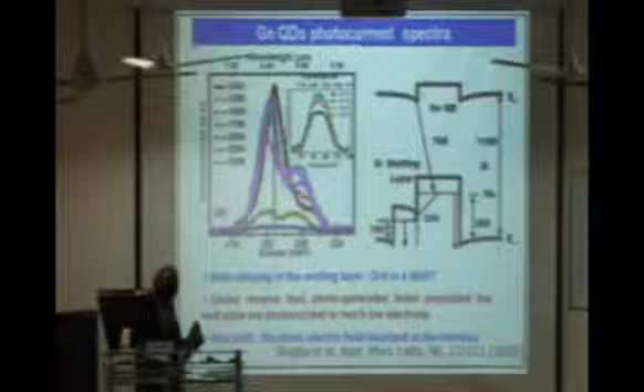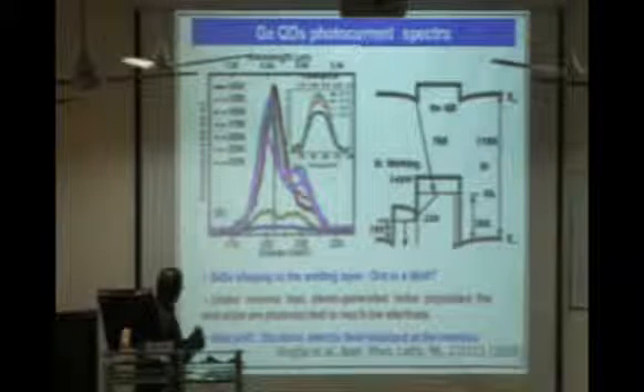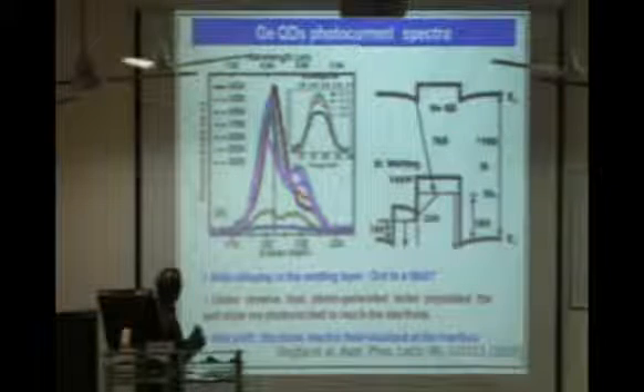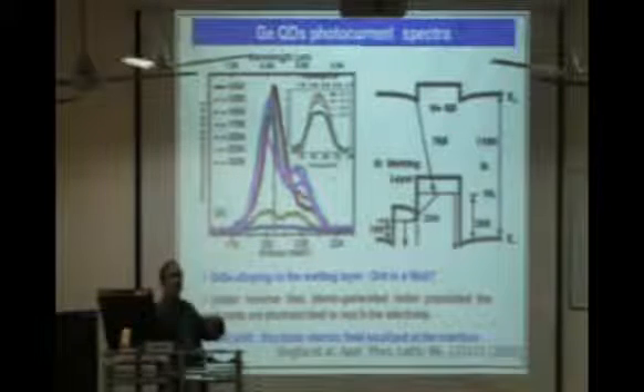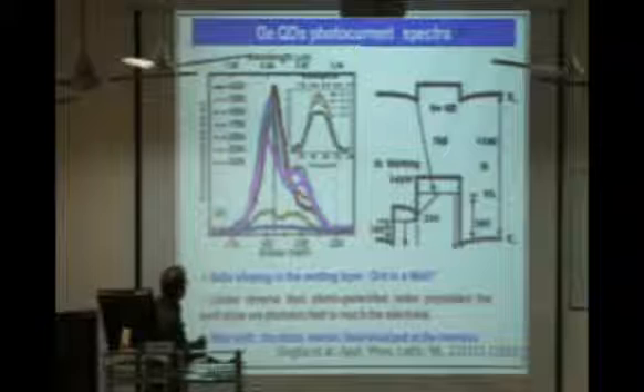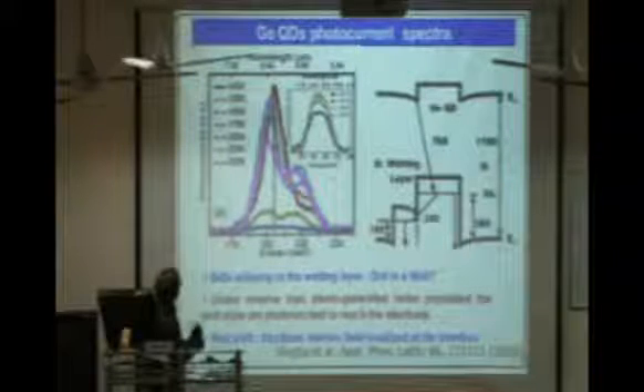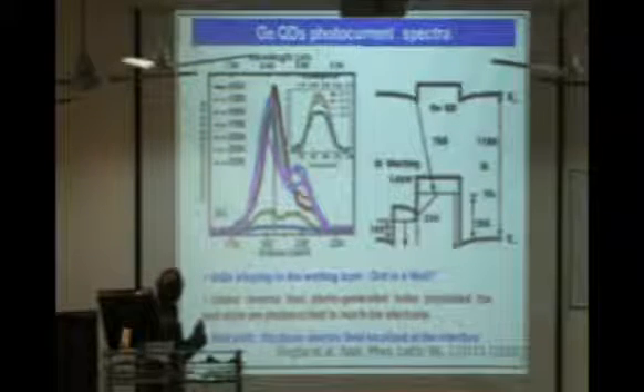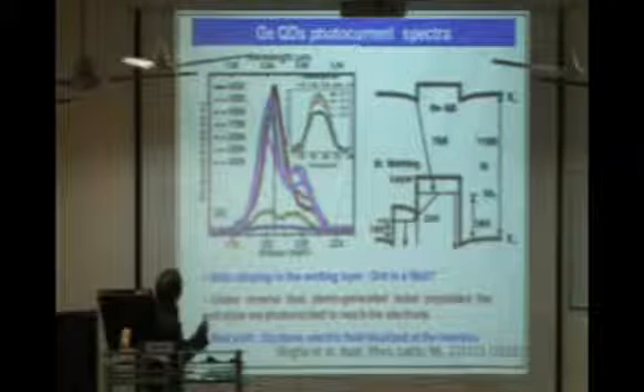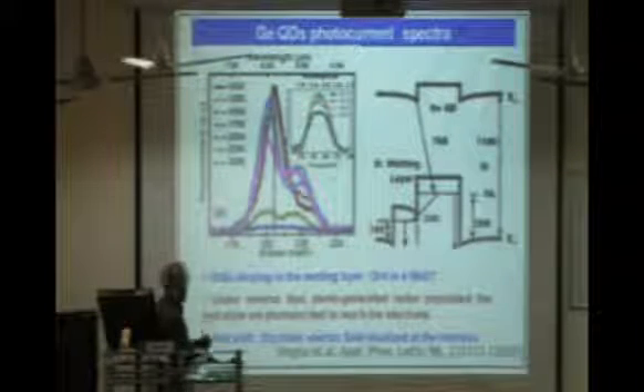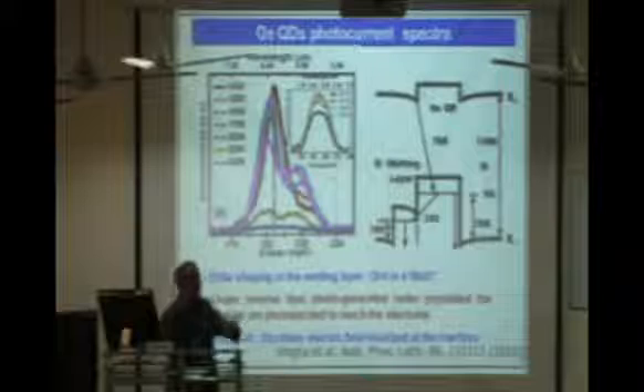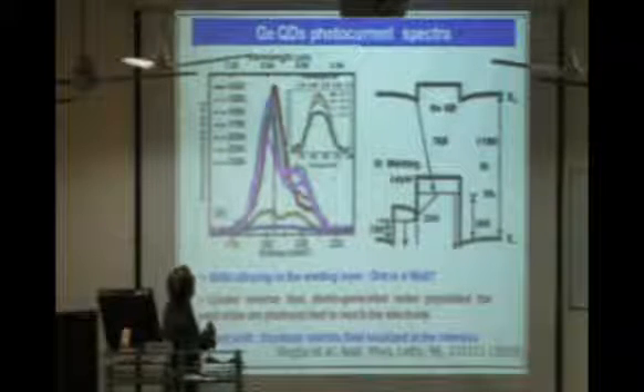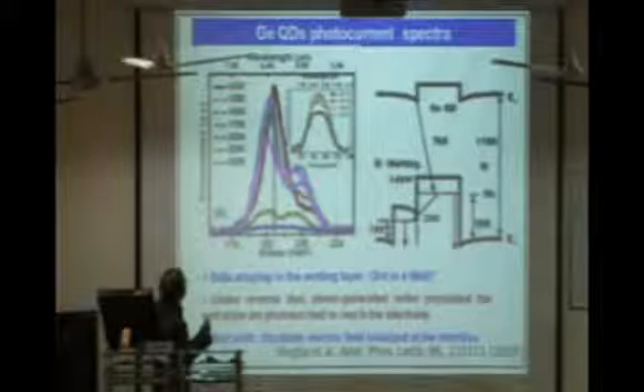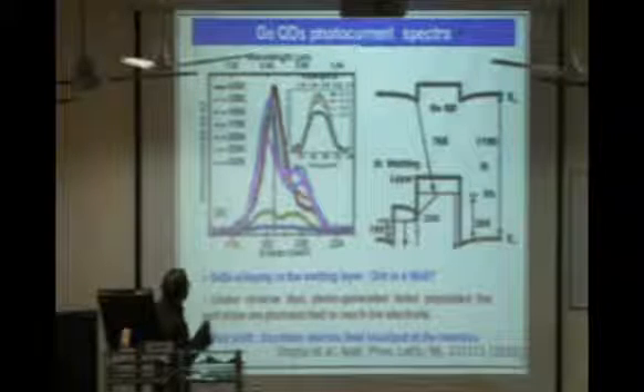And as you see, this works at room temperature because in these quantum dots the leakage current is very, very low. Of course, the noise is very high, but as you cool them, their photo response is very, very high, and this gives rise to detection. And this works at a very low voltage. Normally, for a photodetector you always have to bias it, but in this case, even at a bias as low as 0.1 volt, it gets a very good photo response.